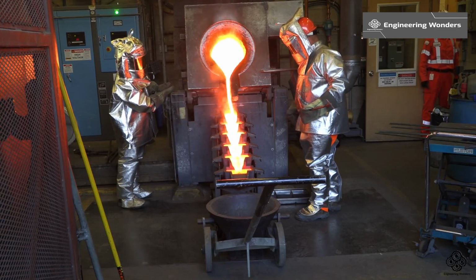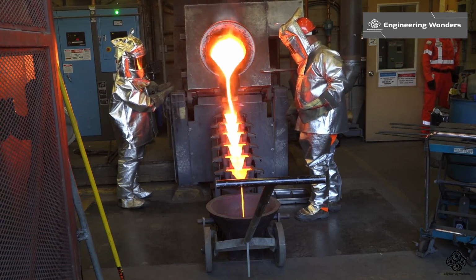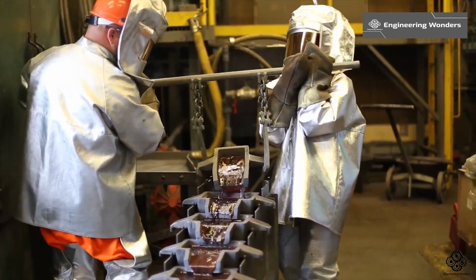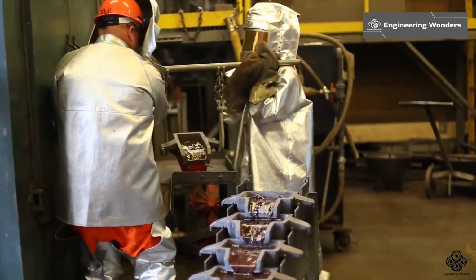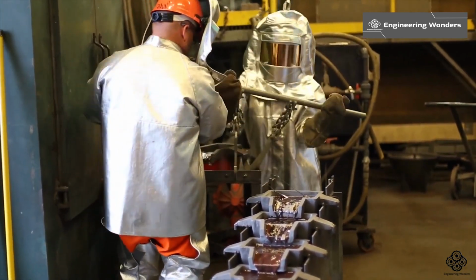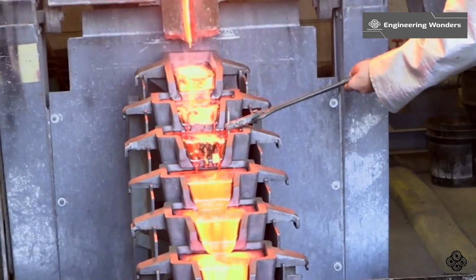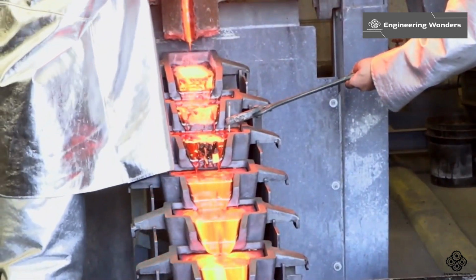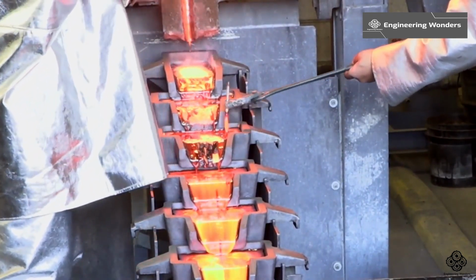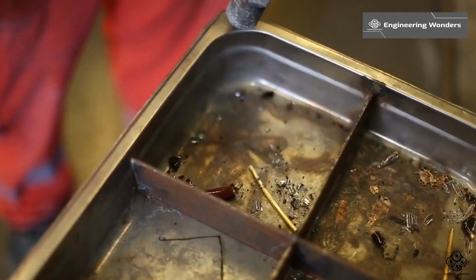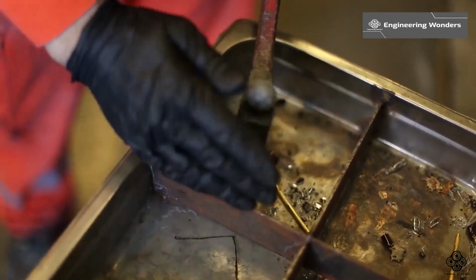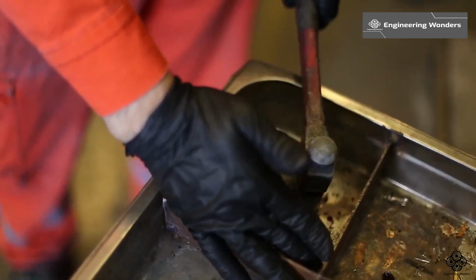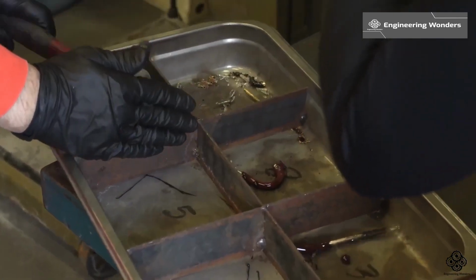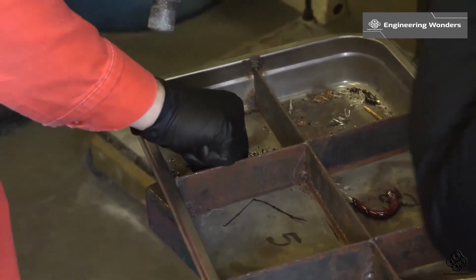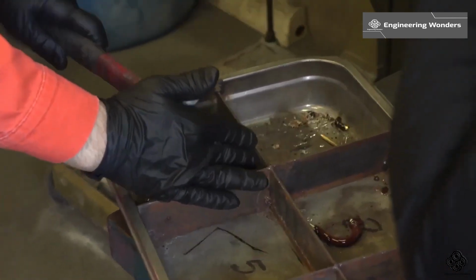After the molten gold is poured into molds to form bars, a sample is extracted to determine the gold and silver content. This sample is carefully taken and analyzed to assess the purity of the gold. Typically, the gold content in the bars ranges from 80 to 90%, indicating a high concentration of pure gold. Additionally, the sample is also examined for its silver content, which usually falls between 6 to 12%.